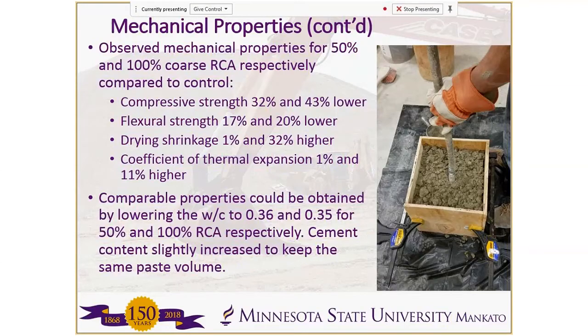So the observed mechanical properties that we got from those experiments for 50% and 100% coarse RCA substitution, our compressive strengths were about 32% and 43% lower. If you remember, I said if you use lower water cement ratio, you would kind of expect to see more of a difference between compressive strengths. Flexural strength was about 17 to 20% lower. Drying shrinkage was 1 and 32% higher, and coefficient of thermal expansion was 1% and 11% higher.